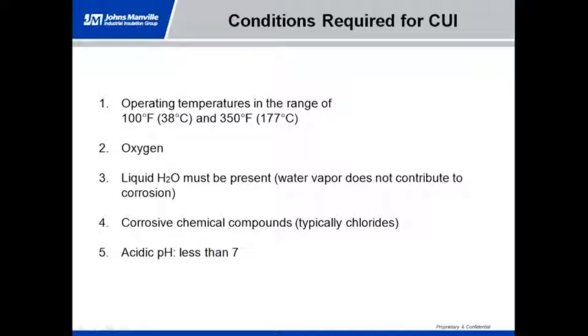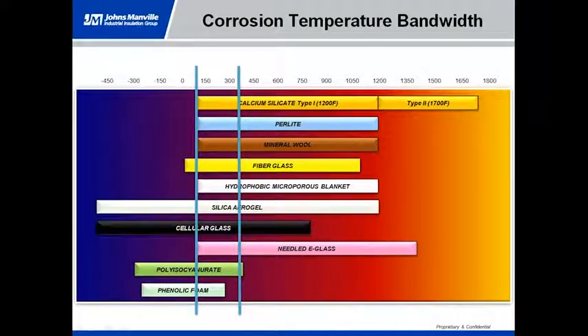Now, what we need for corrosion to happen is an operating temperature of 100 to 350 degrees. Corrosion can also occur outside of that range, and I think we know that, but this is the sweet spot for corrosion. We need oxygen, we need liquid water to be present. Now, water vapor or high humidity conditions doesn't contribute to corrosion. You need to have a liquid to help conduct or facilitate corrosion. You need corrosive chemical compounds, which are typically chlorides found in seawater and drinking water, and then acidic pH, which means it has to have a pH value of less than 7.